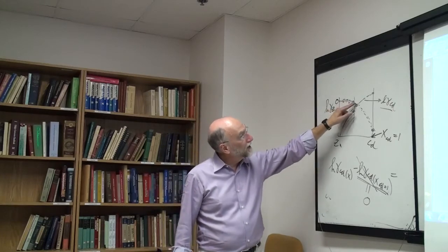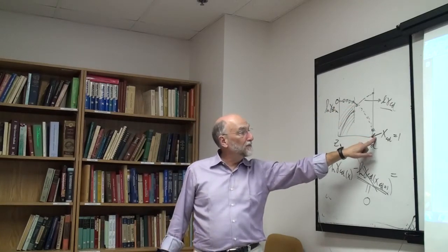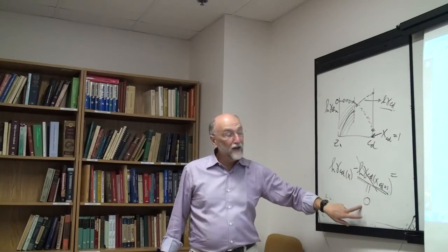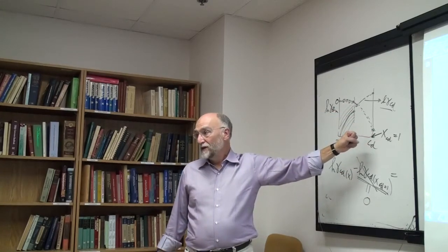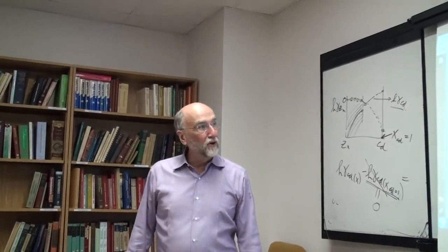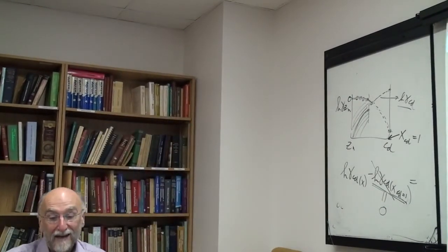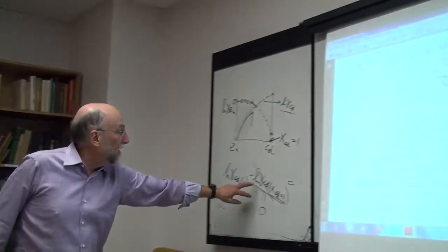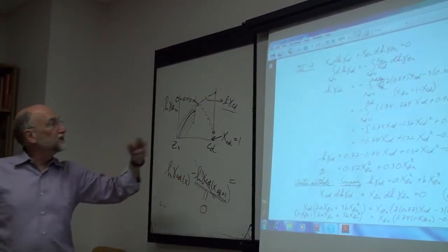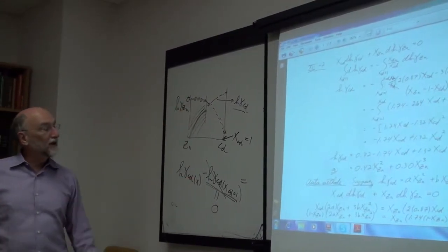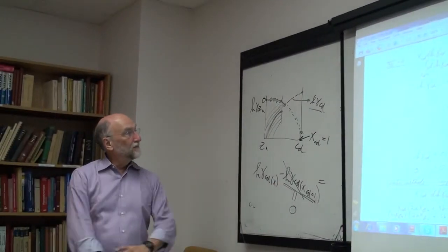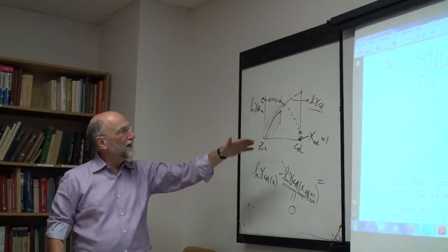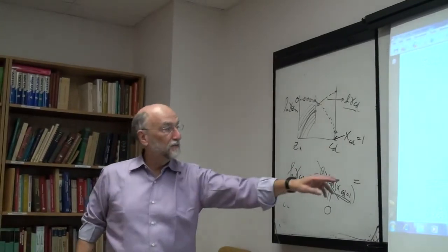If I don't, I can extrapolate this all the way over to pure cadmium and use this as my endpoint, but then I'm basing the whole thing upon an extrapolation. Now, when you do this on the computer, the computer automatically uses this endpoint value. So if I give it this equation for log gamma zinc, the computer is going to put this in automatically, because it extrapolates, and it's going to give you this expression for log gamma cadmium.